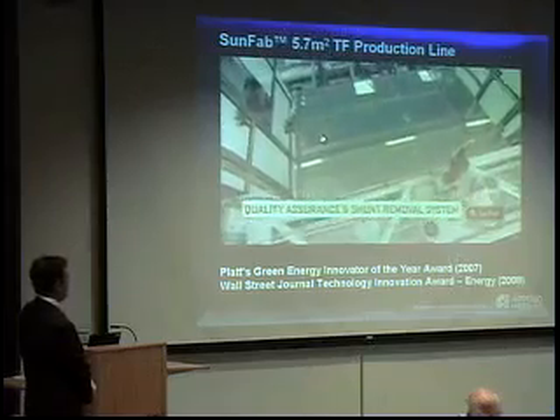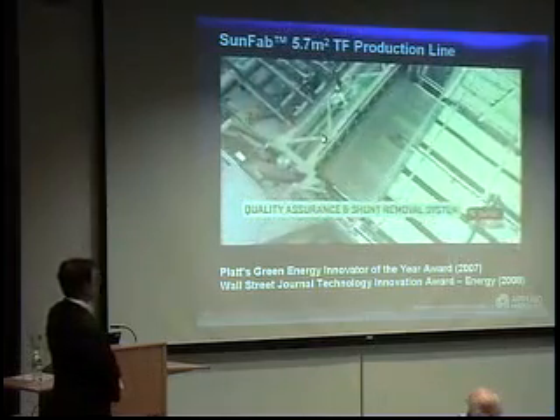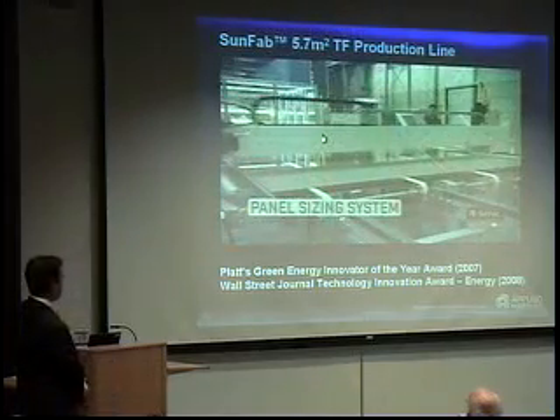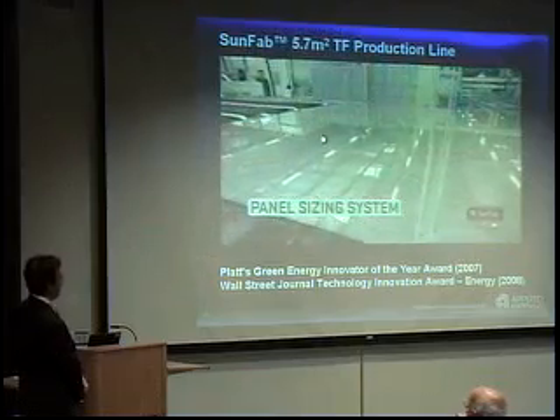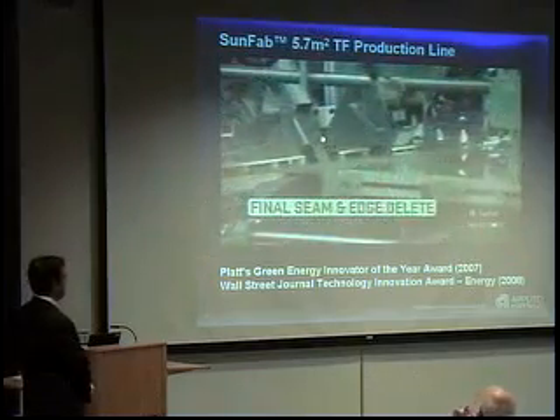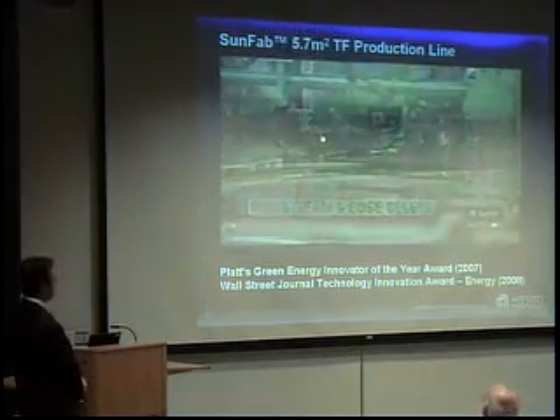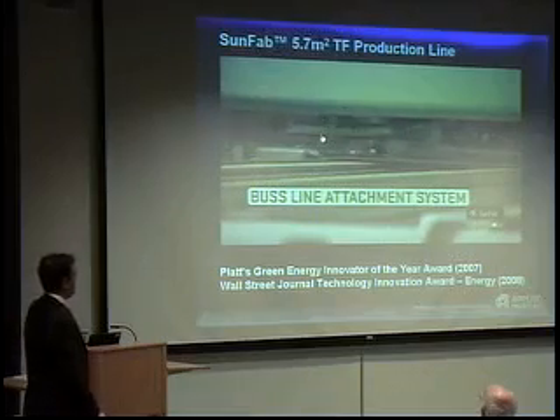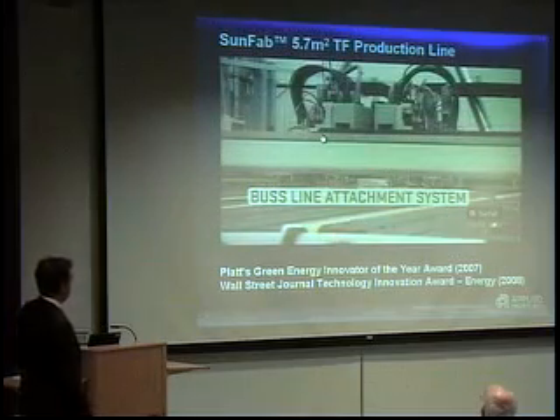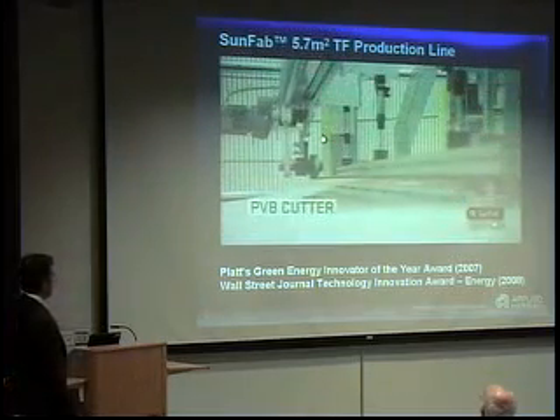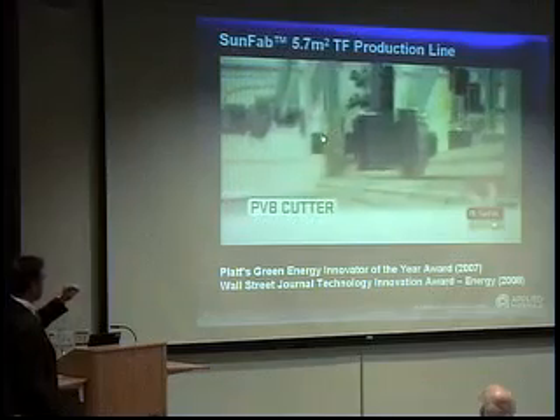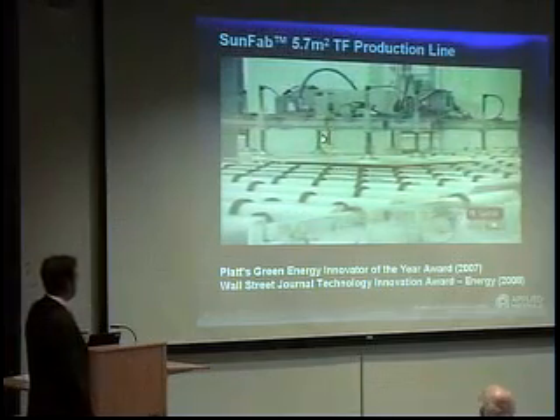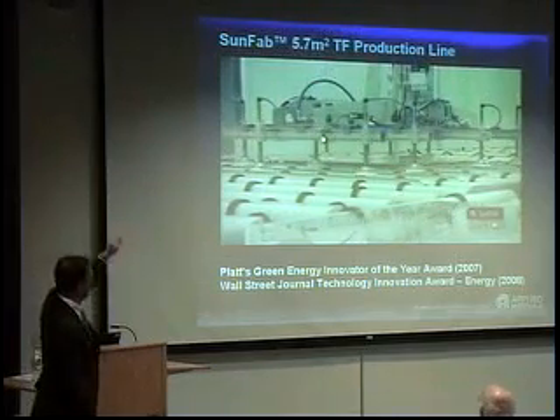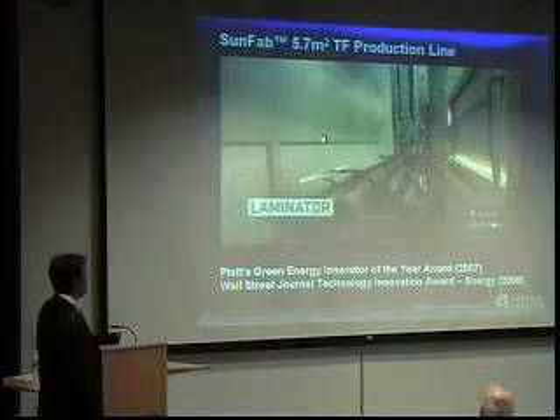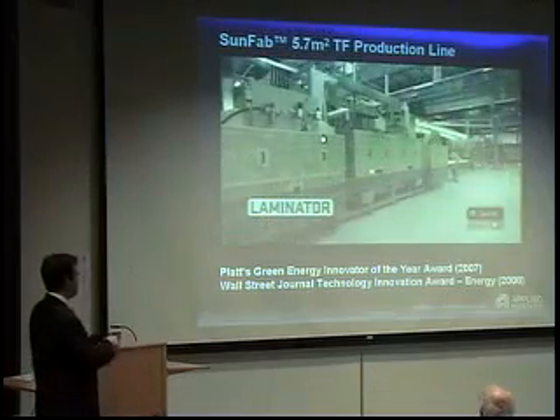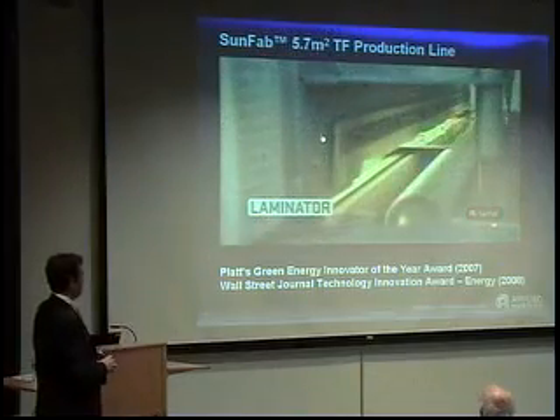Now you do what's called shunt busting. You fix some yield problems. You can then cut the panels into multiple sizes at this point because all the expensive processing is done. Fix the edges. Attach a bus line to connect up all the cells. This is a PVB. This is the material that seals the 2 glass layers together, like in your windshield. Put the other layer of glass on, laminate it, heat it up, and make the material flow.